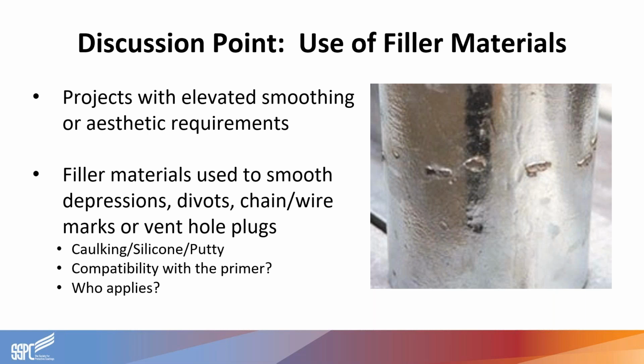But you'll want to confirm with the paint manufacturer whether that specified filler material is going to be compatible with the primer coat. And just be sure to identify who would actually be responsible for acquiring, applying, and smoothing that filler material.